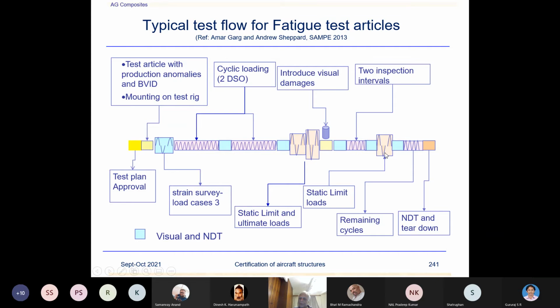So it was loaded to limit load carrying capability to see if this VID or visible damage grows or not. Then static. After that, we loaded to the remaining cycles. Now, we loaded it to the 3 DSO, the remaining cycles, just to be conservative, but it was not the requirement of the regulator. So essentially, it was loaded to 3 DSOs.